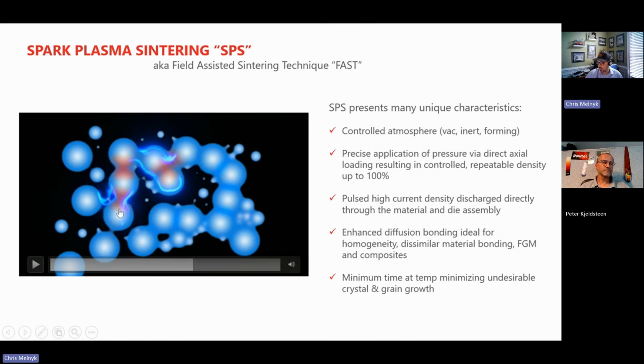So when they started SPSing, they noticed those oxides were gone, and we were getting great interparticle bonding. And so I think someone speculated that to get rid of that oxide, there must have been thousands of degrees. And since this whole thing is done in a vacuum and there's a potential difference between the top and bottom, and we're applying a discharge, that's a recipe for plasma, because in a vacuum with a DC voltage, that's how you make plasma. So I think someone speculated that must be the mechanism that's removing that oxide. But I think that's been pretty settled that's disproven. And really what's happening here is just a very localized Joule heating.